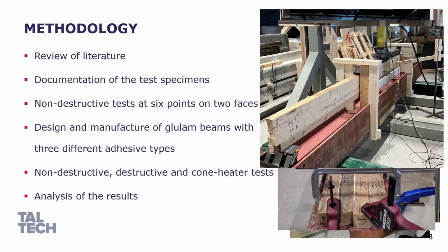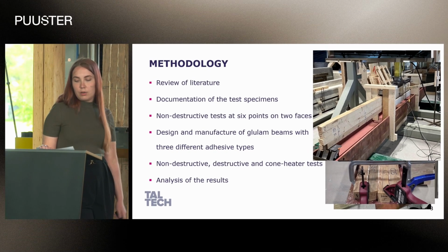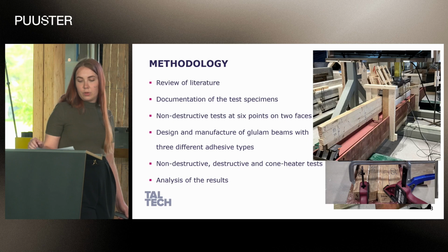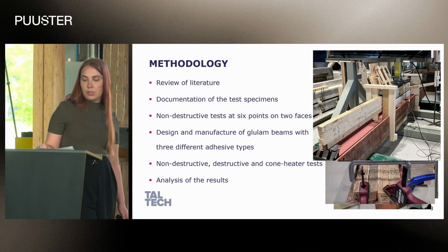Non-destructive bending tests were performed on all of the glulam beams to find the global and local MOEs, and also a 4-point destructive bending test was performed on 3 glulam beams that were bonded with all 3 different adhesive types. And finally, cone heater tests were performed on all 3 adhesive types to evaluate the bond line integrity at elevated temperatures.